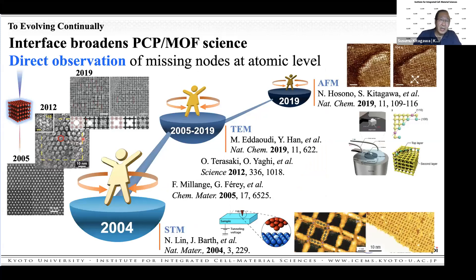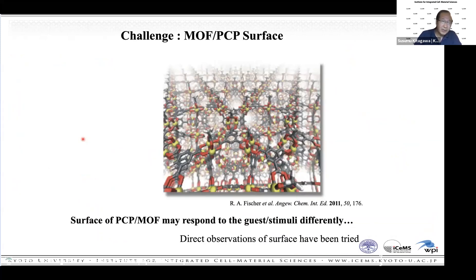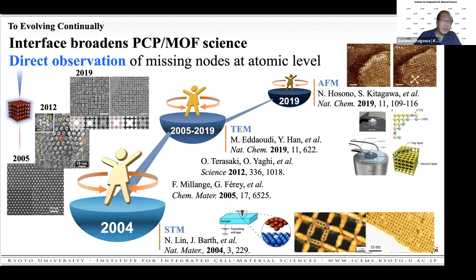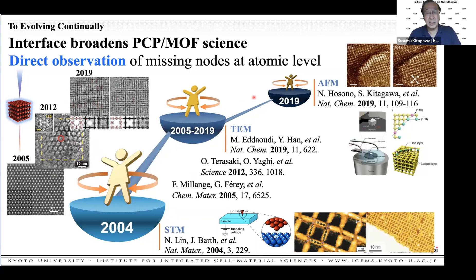The surface is very interesting but difficult to see. Historically, Nian Lin at the Max Planck Institute observed copper-organic molecule one-molecule-thin layer systems using STM. After that, several groups observed the surface of MOF compounds using TEM. We want to see the adsorption profile on the surface, so we carried out AFM observations. Using specific ligands, we synthesized a framework structure — a single layer of bulk crystals in the tetragonal form when vacant.